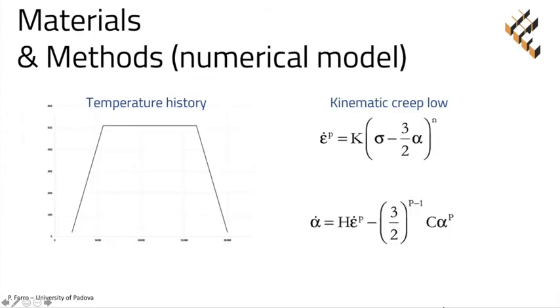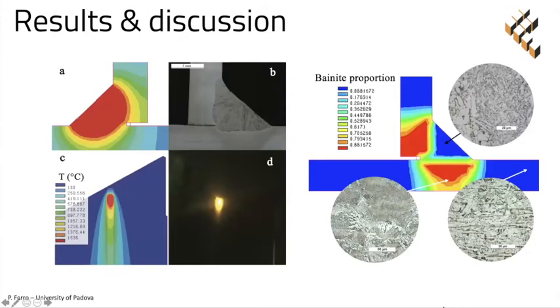After welding simulation, the joint underwent the furnace thermal history used to carry out the experimental stress relief heat treatment, as you can see in the figure on the left. In the mechanical computation, the viscoplastic deformation of the alloy was modeled by using the creep law written on the right side of this slide, where alpha is the kinematic strain hardening variable and H, K, C, P and N are temperature dependent parameters.